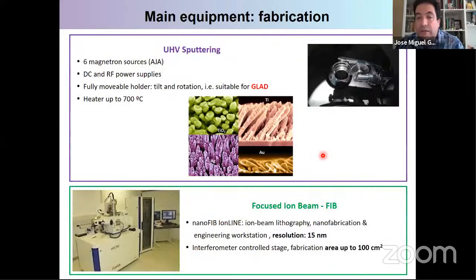We have a homemade ultra-high vacuum sputtering with 6 magnetron sources. And what is very important for us is that the substrate can be tilted and can rotate also. So it's very suitable for glancing angle deposition. And this is what allows us to fabricate nanocolumns with the sputtering. We also have a focused ion beam that can pattern large areas up to 100 square centimeters with a resolution down to 15 nanometers. Those are, let's say, the main features regarding fabrication.